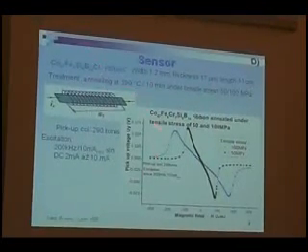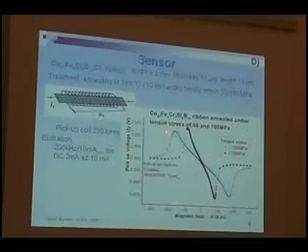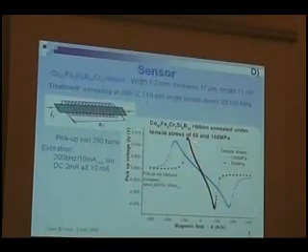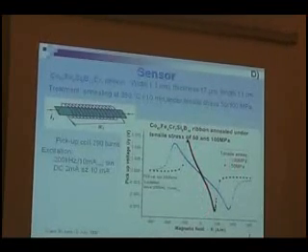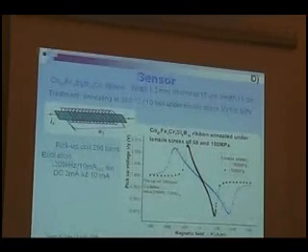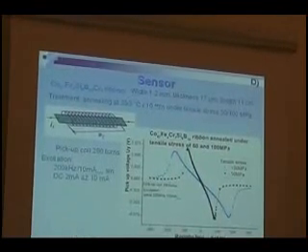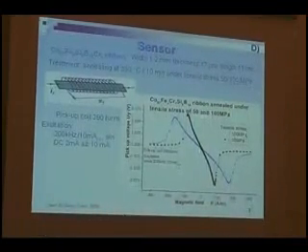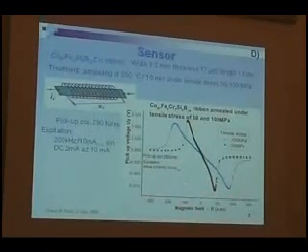Moreover, here you can see this one ribbon annealed for 100 megapascal, which is the response in blue, and the other ribbon was annealed under 50 megapascal, and the response is the black one. The higher the tensile stress applied during the annealing, the larger is the anisotropy field induced, and wider is the quasi-linear part of the response.